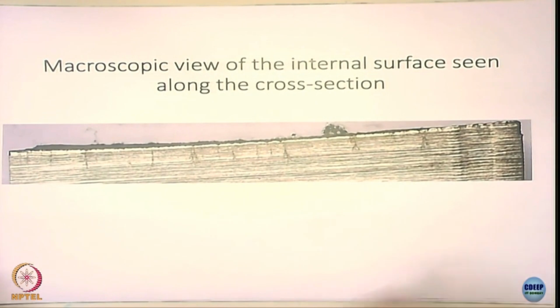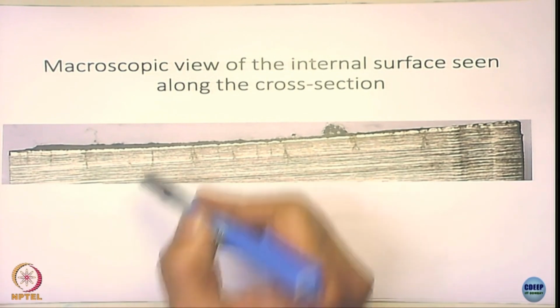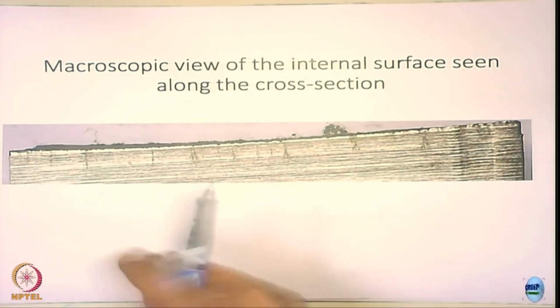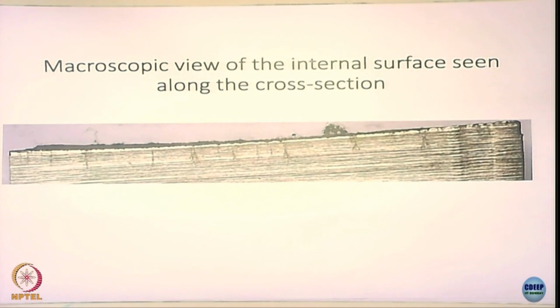And if I look at the inner walls of the reactor, normally we do NDT, right? One very versatile NDT is dye penetrant test. Some of you are aware of it, right? You apply a dye on the surface and you wipe them out, and you also add another eluant to the surface, and so the dye comes to the surface, and wherever the crack is, the dye penetrates and comes back. So you will be able to see the subsurface cracks, even surface cracks, using the dye penetrant test.